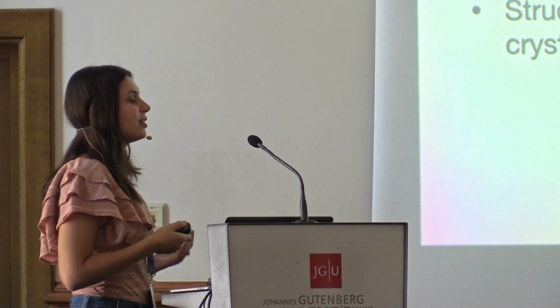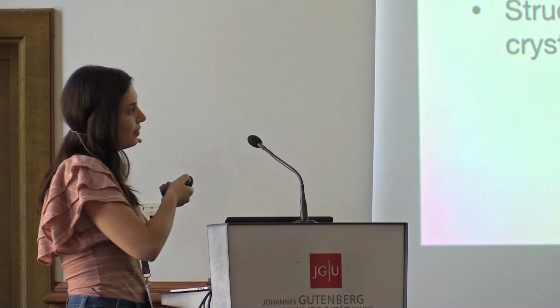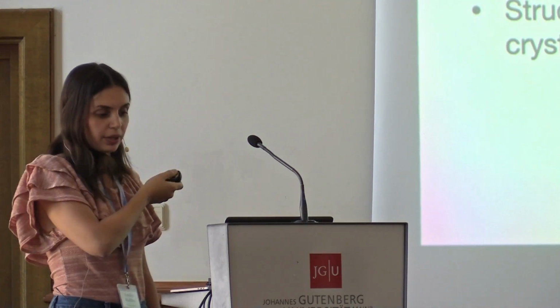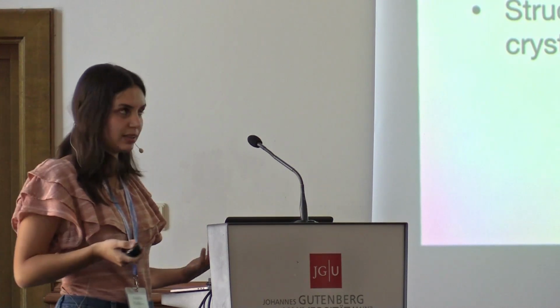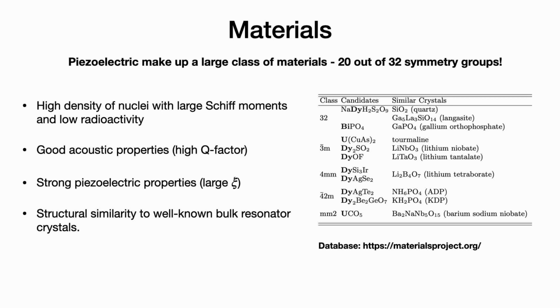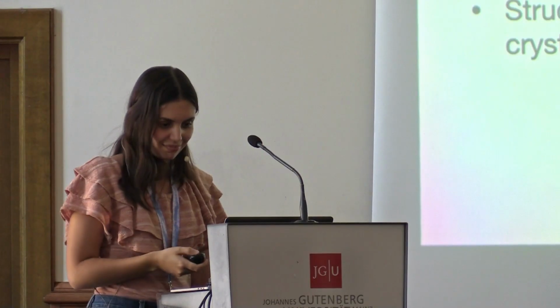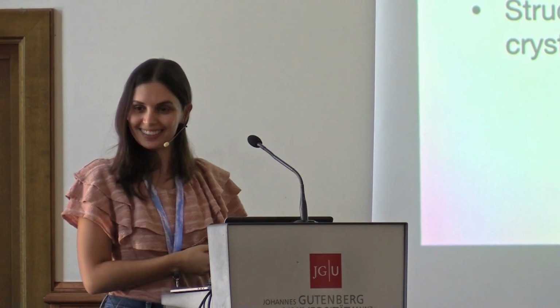And finally, since we're dealing with materials that are not necessarily very well studied, it helps if they have some structural similarity to a material that we already use in bulk resonators, for example, something that had the same symmetry properties as quartz. We didn't find a commercially manufactured material that satisfies all of these at the moment. However, there's a database at the Materials Project where you can categorize experimentally verified materials by their symmetry structure, their density, and which nuclei they contain. This is just a small subset of potential materials that we found that are similar to known crystals and have the right kind of nuclei in them. Okay, I think I'll stop there then.